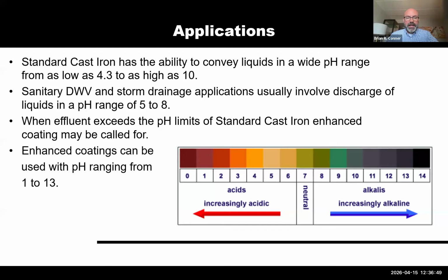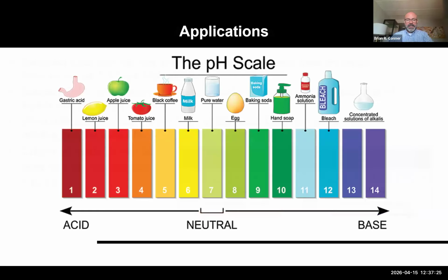And this coating is an epoxy e-coat. So similarly to how we coat all of our standard fittings, we do a cathodic and anodic epoxy e-coat on our pipe and our fittings for Edge HP, both on the inside of the pipe and the exterior of the pipe, giving enhanced corrosion protection to both internal effluents that might cause corrosion and any external threats that may come in contact with cast iron.